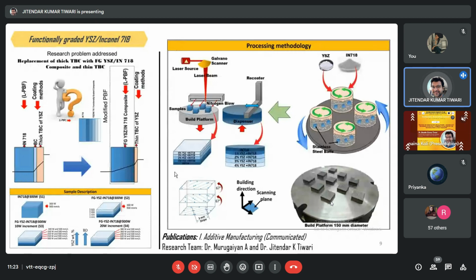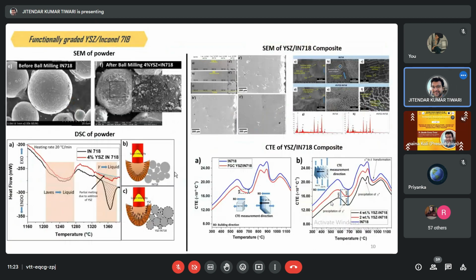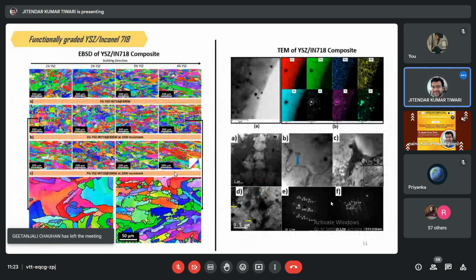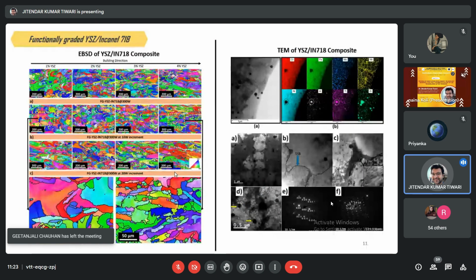So the composition gradation results I have already shown. These are the composition gradation results. There are much more results. So actually, yttria stabilized zirconia addition refines the structure. So as you can see, the grain structure is refined after the addition of yttria stabilized zirconia.